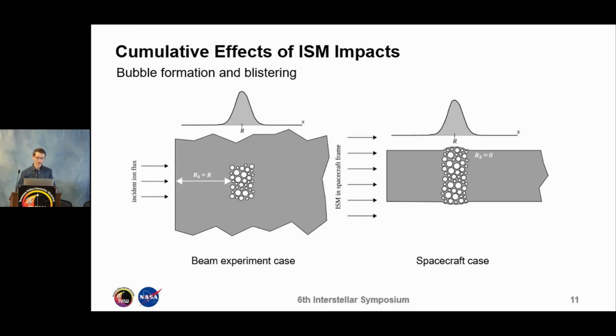So there are 2 kinds of cases that we can discuss. Most of the literature on bubble formation is done in beamed experiment cases where you have a target which is much larger in general than your beam size. Now this leads to a distance where the material will implant itself below the surface at a distance which is comparable to the range. The distance to the nearest surface from the implanted species is comparable to the range of the implantation distribution because the closest surface is the surface of impact.